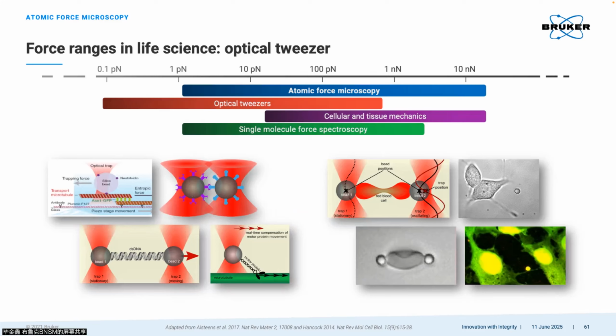Comparing the optical tweezer with AFM, you will see that the force range of the optical tweezer is much lower, and we have a higher force resolution, maybe up to 0.1 piconewton, with a force range from around 1 piconewton to just 1 nanonewton. If we want to measure, for example, cell adhesion at a range of several nanonewtons, it's maybe better to use the AFM. But for the whole study, we studied molecular things, and we also studied cell mechanics.